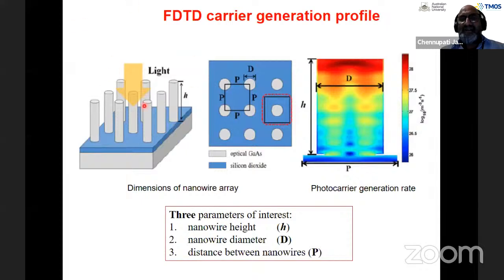So we've done extensive simulations again. What should be the height of the nanowire? What should be the diameter of the nanowire? What should be the distance between the nanowires? You can see that most of the current is generated at the tip of the nanowire, indicating that you don't need to make long nanowires. 1 or 2 micron nanowires are sufficient.